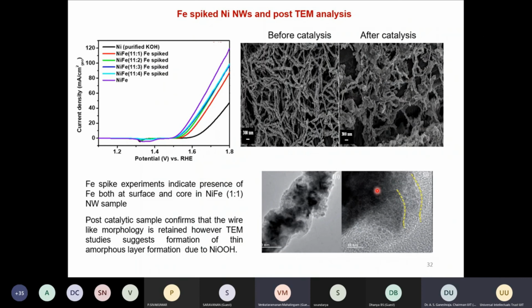For catalysis, an amorphous layer is something very important. They show better activity compared to the crystalline material, and this is due to the formation of nickel oxyhydroxide, which happened during the oxidation process. So this nickel oxyhydroxide formation is necessary for the improved catalytic activity.